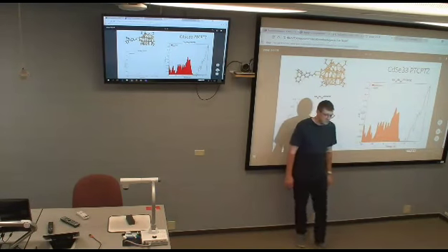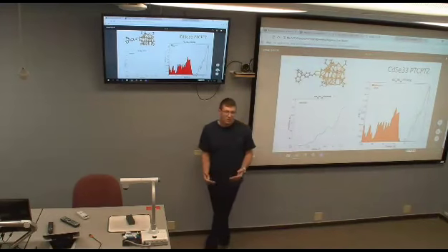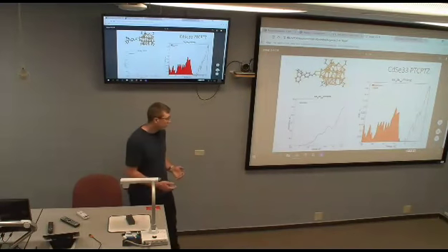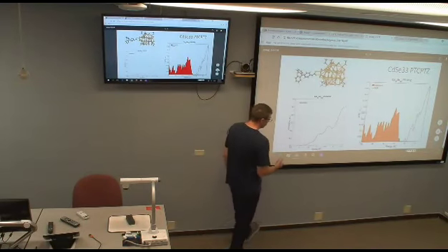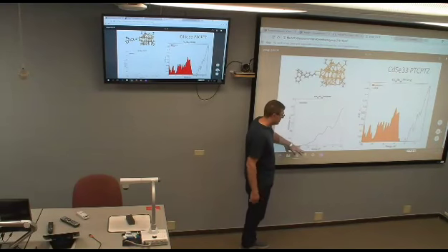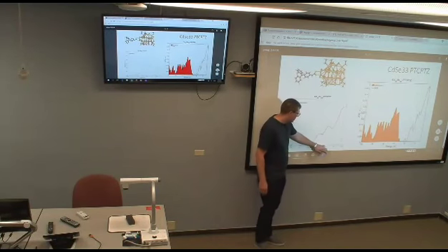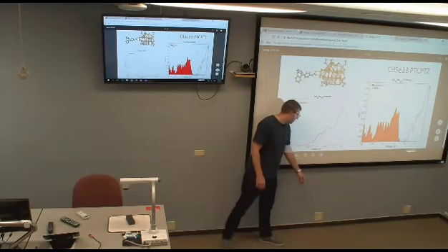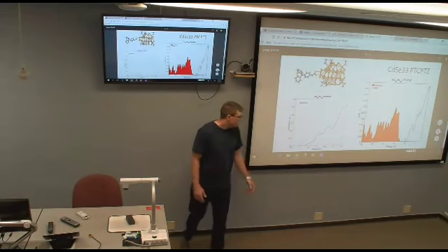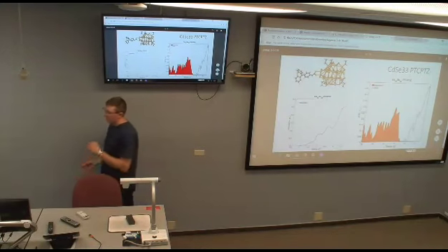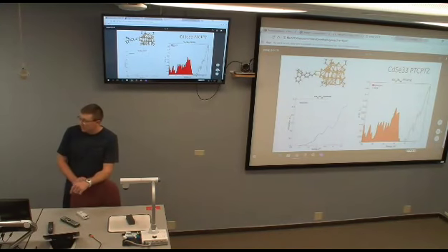So the gap is going to be more closed than what it was for the carboxylic linker group. And same issue again. There's still some primary peaks around 2.8 where the major onset should be, but because of this reduced gap, and also.